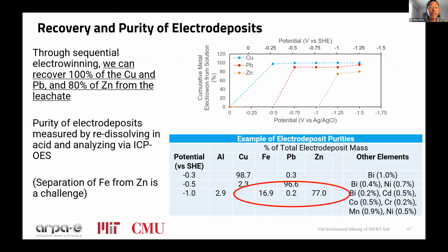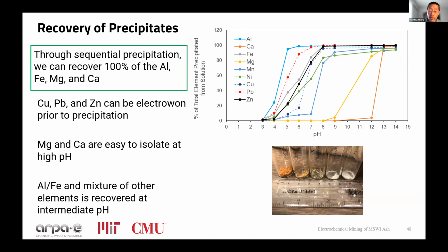Okay? And so what you see is that, as you go down the electrochemical series and systematically vary potential, what you do is to sequentially separate out the metals. And so right now, at this point, we don't have great separation of iron and zinc, but the lead is pretty easy. Okay. What you have left after electrowinning, you can then precipitate with the base. Okay? And so this is actually an experiment where we didn't take out any of the electrowon metals.